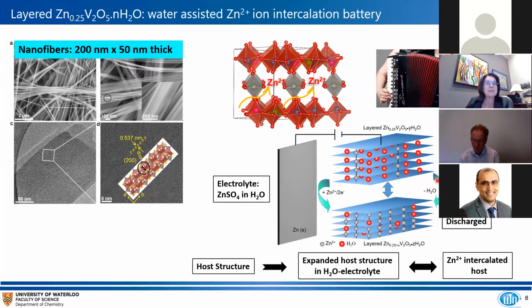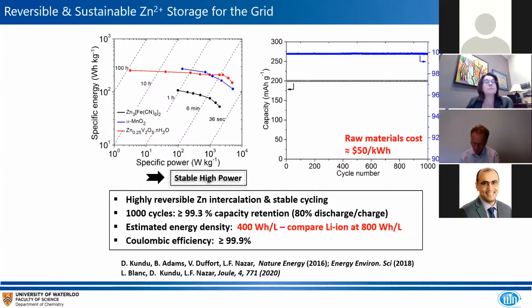And this expansion and contraction is important. And the fact that we are working with a nanostructured material allows that to occur more readily than it would in the bulk. And in fact, when we've tried to make systems that rely on a bulk material such as this, it really doesn't work very well at all.